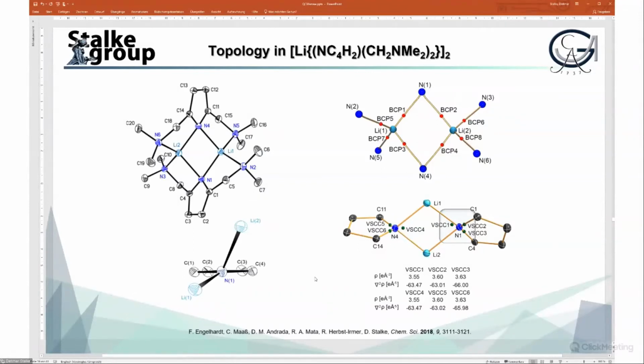We anticipated, of course, 4 of them, because the bonding to the lithium was anticipated to come up with a VSCC, but they didn't. That, of course, would mean we have different bonding in here. So if we look at N1, then lithium-1 is more or less in the plane of the ring. That would mean this VSCC is very close to the lithium and almost on the bond path, which would mean we had a hybridization that could be rationalized as a more or less covalent, orbital-controlled bonding to that lithium.